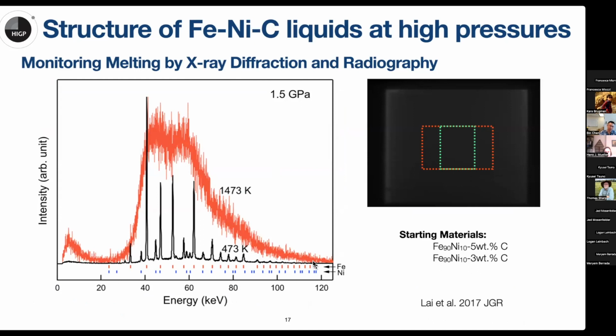The energy dispersive X-ray diffraction pattern of a liquid phase is very distinctive from the X-ray diffraction pattern of a solid phase. This black line is the X-ray diffraction pattern of iron and nickel mixed with carbon, and after it is molten, we can just see a bump in the X-ray diffraction pattern. So we measured the X-ray diffraction pattern at various theta angles for iron nickel carbon with 5% carbon and iron nickel with 3% carbon.